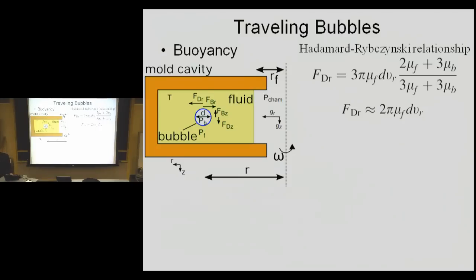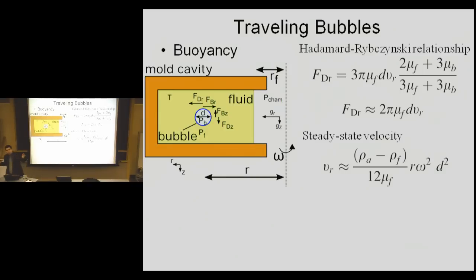So the first mechanism for removing bubbles is buoyancy, as we've been talking about, right? You have a mass of the bubbles, which we consider very negligible compared to the amount of acceleration we're introducing on the displaced volume of fluid. But there's technically an MA term, and we have buoyant force on these bubbles, and we have drag force, and we then calculate what their velocity should be at any given location.